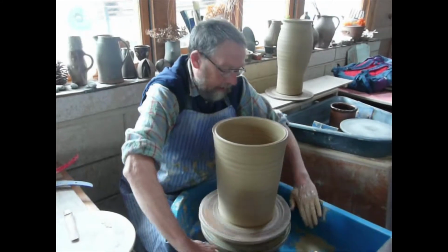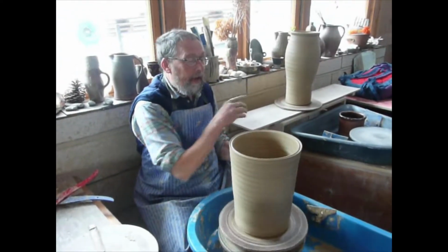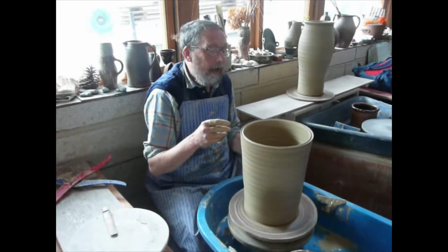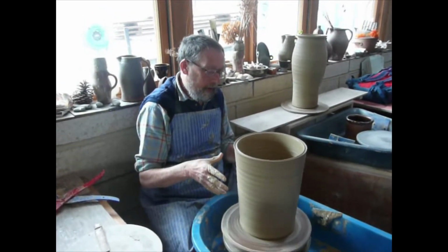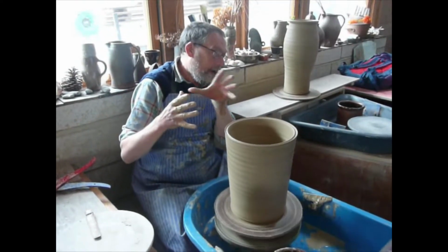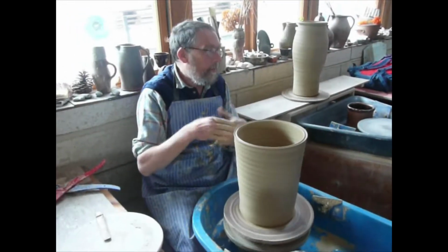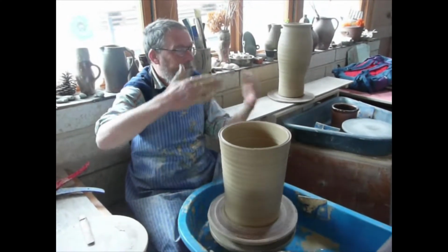Now when I started making these big pots, I just did the same thing as that. I just had a flat top there and a flat top on the top of this thing. And it seemed to work all right. And then one day when I was putting a pot into the kiln, I looked at the bottom, saw there's no glaze on it. A really good pot, I held it up like this, and the top fell off over my shoulder. Because with the big pots, they're all going to be raw glaze, because it's not a thing to biscuit fire.